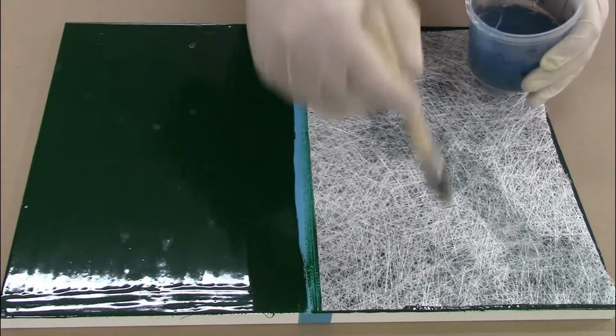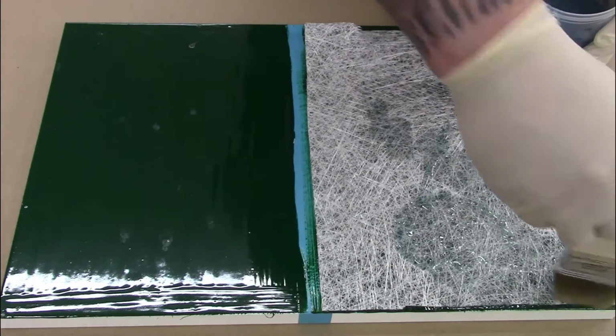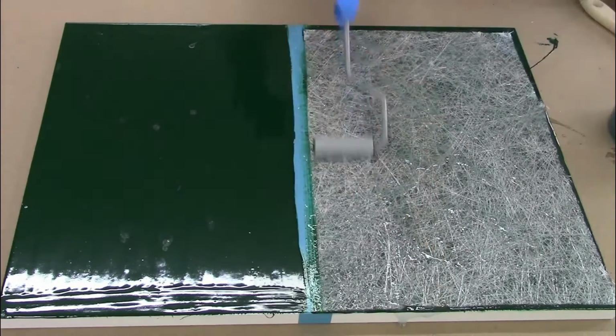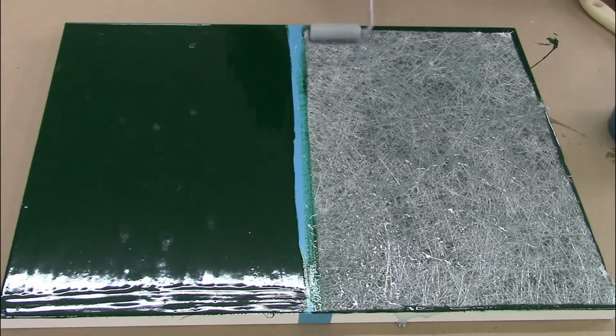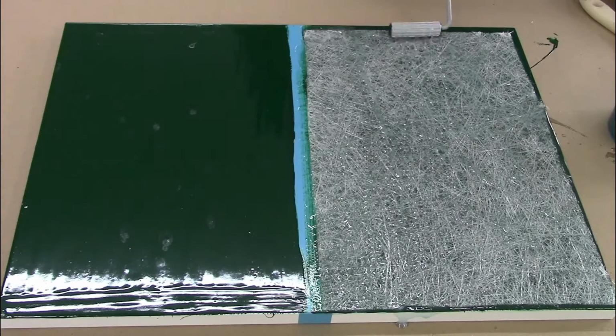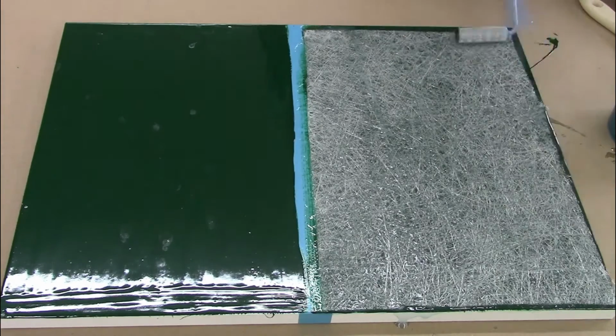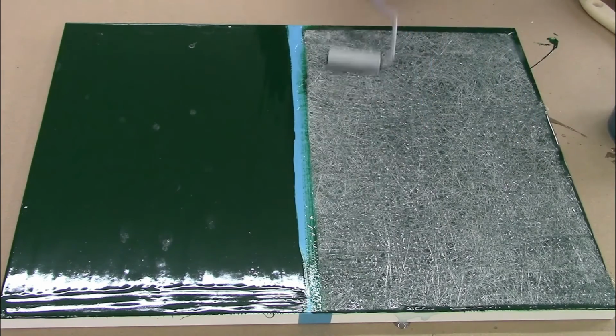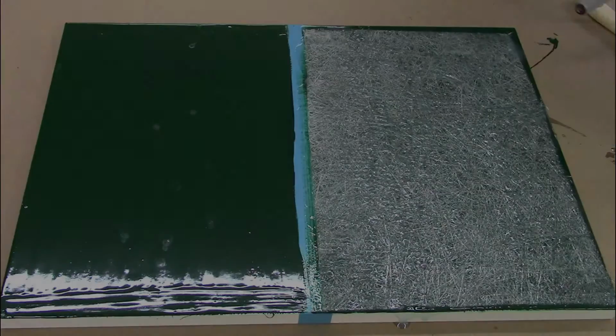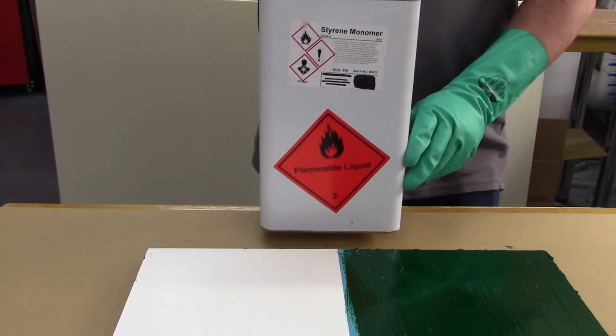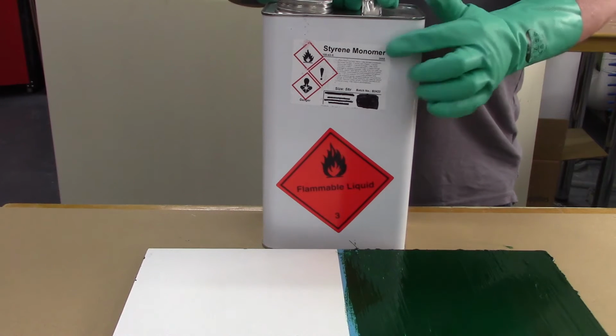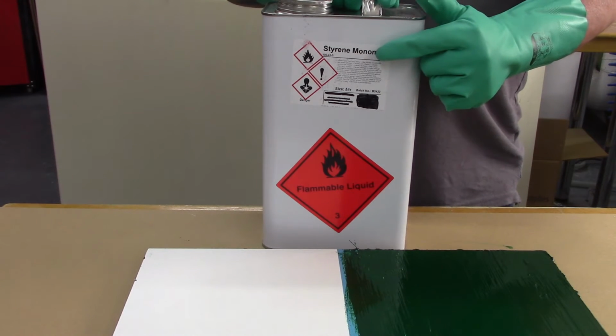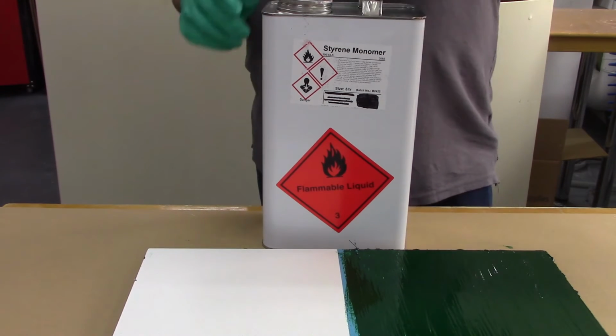After approximately 1.5 to 2 hours, this extremely slow curing resin should cause the Gelcoat to wrinkle as the styrene solvent inside the product starts to attack the Gelcoat. Polyester resins and Gelcoats contain a solvent known as styrene. To demonstrate what styrene does to a Gelcoat when resin takes too long to cure, or if your Gelcoat is too soft, we are brushing pure styrene onto this cured Gelcoat sample.